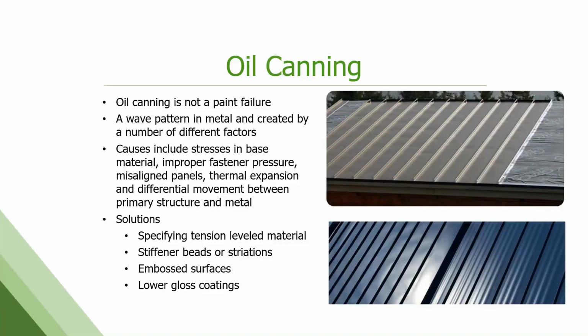There is thermal expansion that plays a part. It may look worse at certain times of the day than other times. There are a couple of ways to combat this. One is making sure that the roll forming process is done very, very well, and that the shape of the panel is ideal. But you can also add stiffener beads or striations to the panels to help take some of that shape out. Embossing the surface helps as well to minimize that. And then lower gloss coatings, which we just recently talked about, low gloss, low sheen, that matte finish masks this quite a bit because you're not seeing that reflection off the surface.